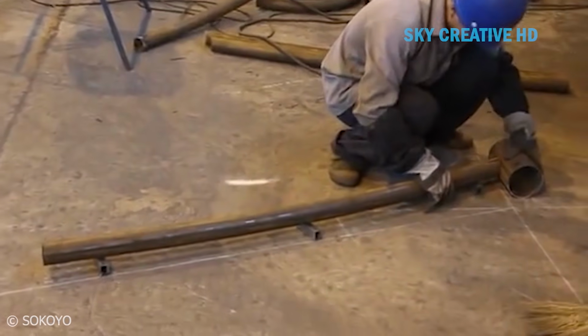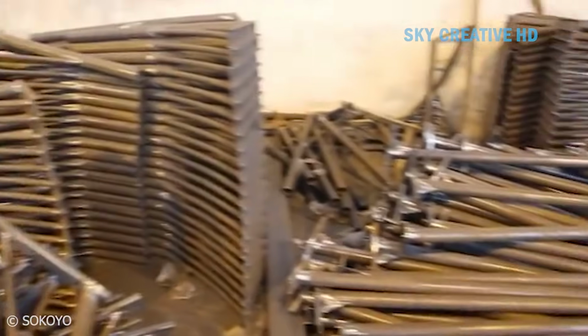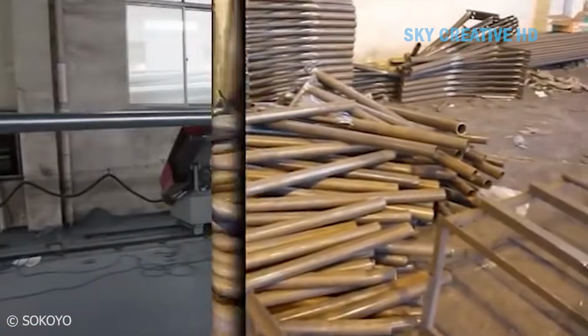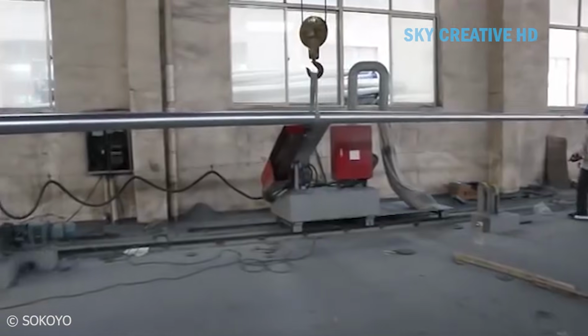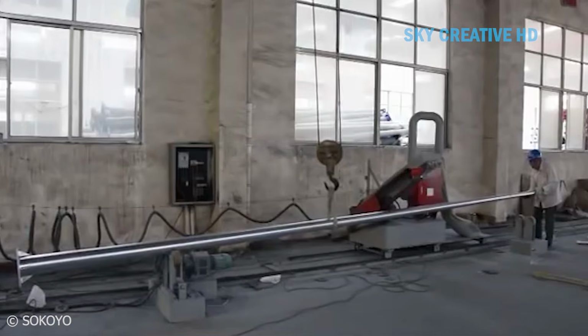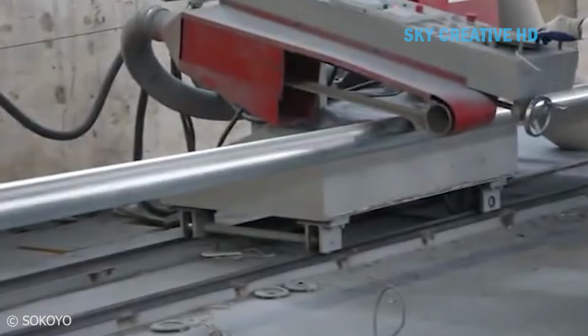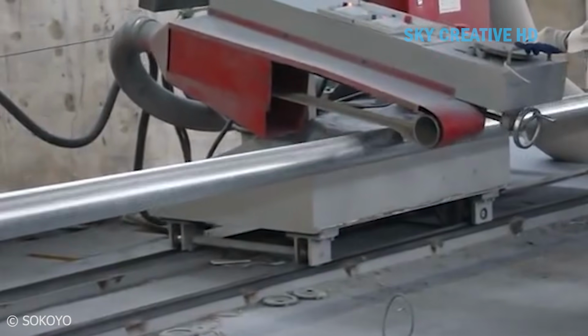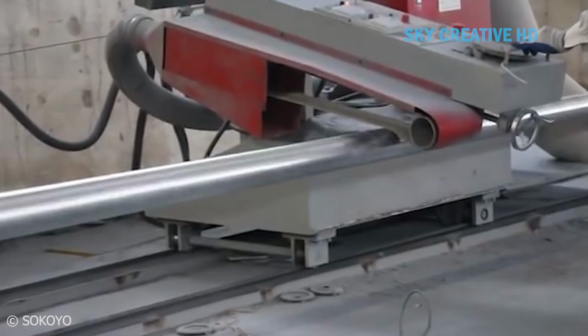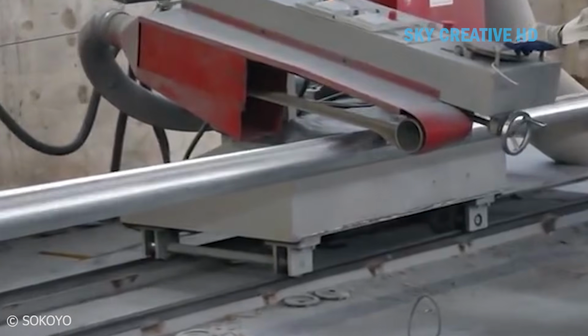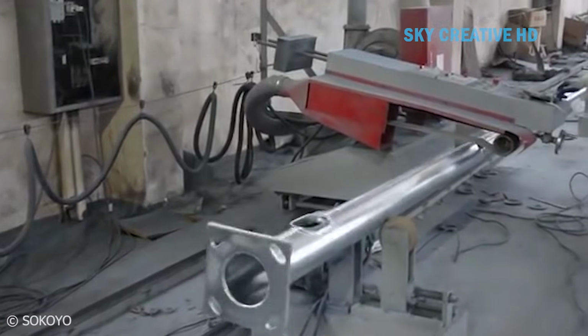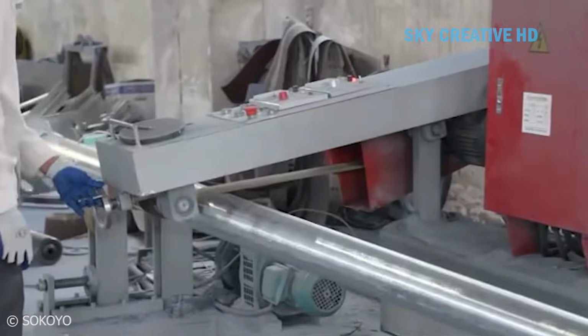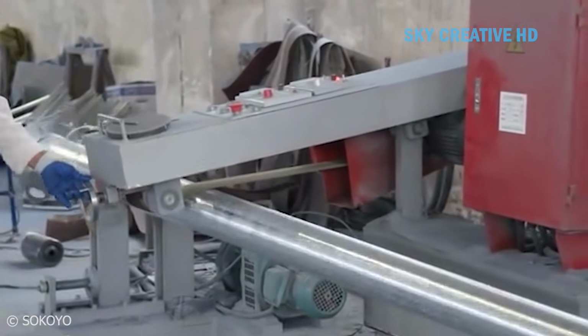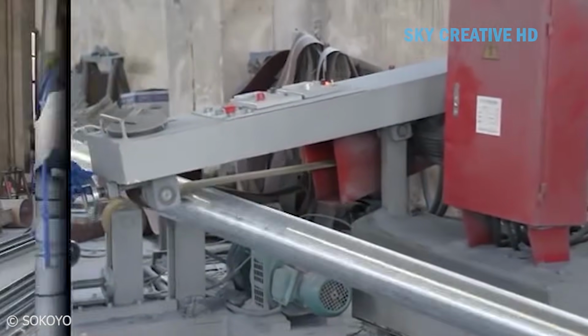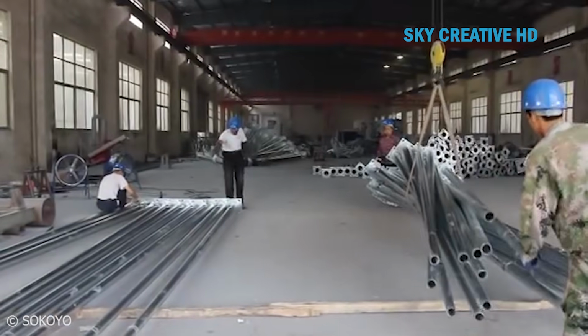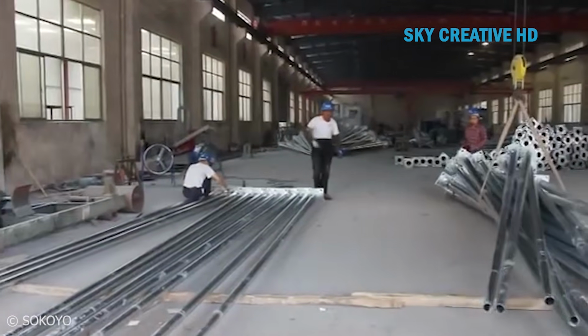After seam welding, the pole goes through a straightening process. Welding introduces heat into one side of the structure, which causes residual stress and a slight bow in the finished assembly. Straightening, using hydraulic or mechanical correction, brings the pole back into alignment within specified tolerances. For a 10-meter pole, the typical straightness specification is within 1/1000 of the pole length, meaning no more than 10 millimeters of deviation over the full height. That's a tight number for a long, relatively slender steel structure.